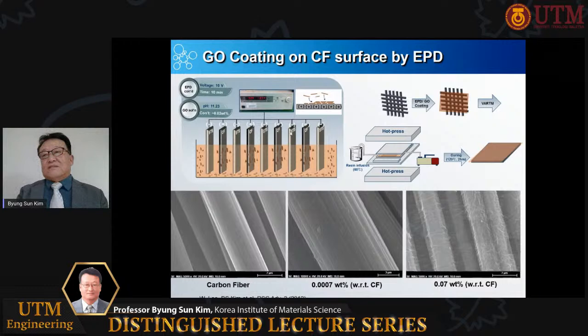Using the sizing agent characteristics of graphene oxide, the electrophoretic deposition process is used. In this process, when the electric field is applied to a substrate in the graphene oxide solution, graphene oxide can be attached to the anode substrate because graphene oxide has negative charge. So here, the carbon fabric is connected to the anode and stainless steel to the cathode as the counter electrode. When the electric field is applied, graphene oxide is coated on the carbon fabric surface. And finally, the graphene oxide coated carbon fabric reinforced composite is dried and stacked to be fabricated using the VARTM process.